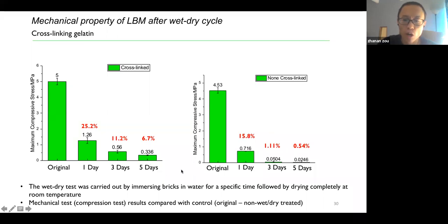And we pull them out and dry them in the air, at room temperature, for almost the same amount of time. And after drying, we use the same machine to carry out the compressive mechanical test, and we compare the mechanical property to the original one, which has never been immersed into the water. So if you look at the left picture, which is the bricks with the cross-linked gelatin, after 1 day immersing in water and completely drying, it still maintains about 25% of the mechanical property, while for the 3 days, there's still like 11%, and 5 days, about 6 to 7%.